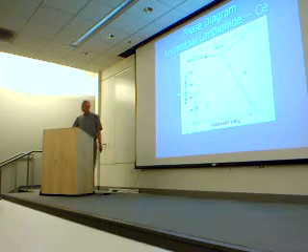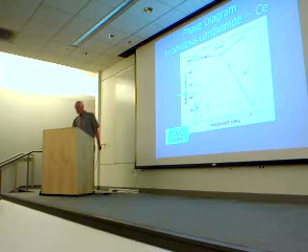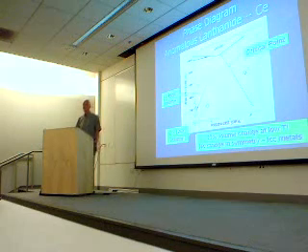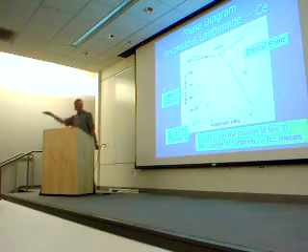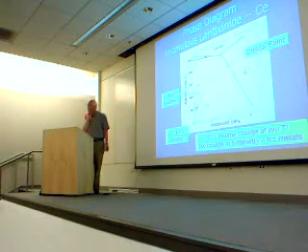Okay, so here's cerium. This is the case that was known a long time ago, and was just presumed that this very large effect that occurs in cerium had to do with a complete change in the character of the f electrons. There's a low volume phase and a high volume phase, and the volumes can differ by as much as 15%. That is a huge change for metals. Have any of you done phase transitions, like silicon melting, for example, or silicon under pressure goes to a metal? The volume change is not this big.